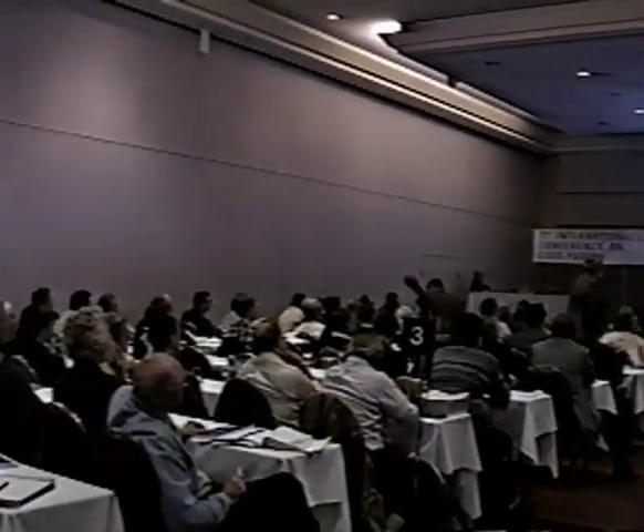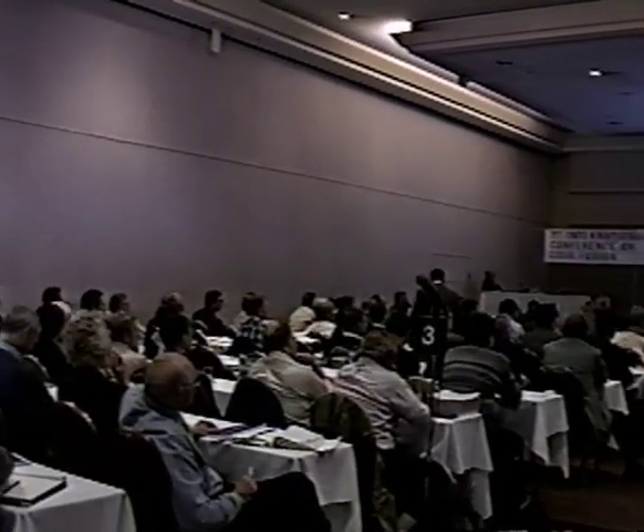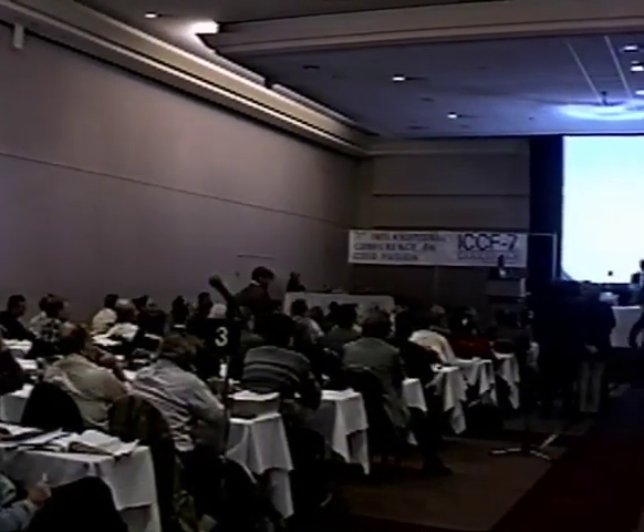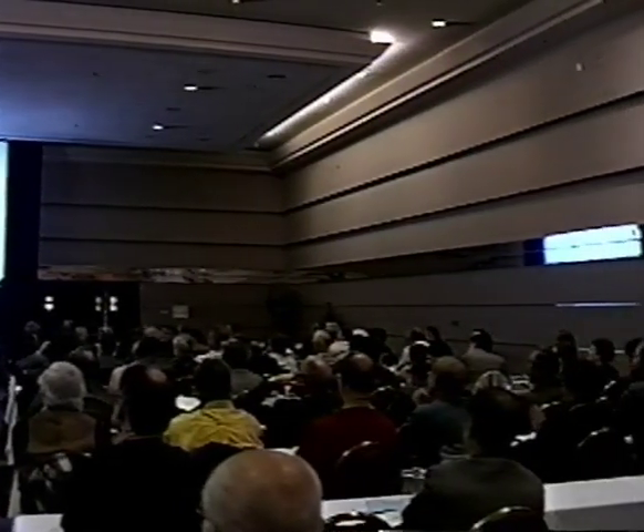Douglas Morrison from Geneva. You've given 2 remarkable discoveries. One is that you can get power produced without any charging, without any electrolysis. This is entirely different from the whole philosophy of cold fusion, which involves electrolysis, and it's very remarkable. And the second remarkable thing is that you have said that the procedure happens very quickly. Almost instantaneously you get power, there's no current, and then when you put on the current, the power rises very quickly. Even though 5 microns is small, this is a very high speed, because there have been many experiments like Mike McKubre's and many other people who said it takes a long time to load. So your results seem in absolute contradiction with everything that's been done for the last 9 years.